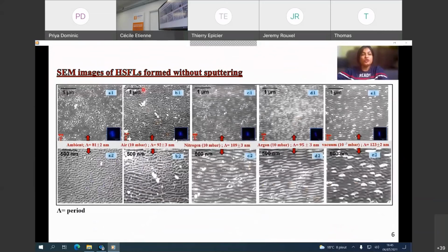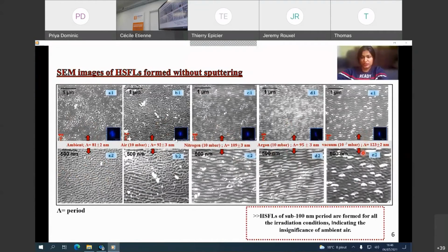So going through the results, first we see the images of HSFL formed without sputtering. We have beautiful HSFL structures, as you can see from the figure, of very small period, which are parallel to the polarization direction of the laser, for ambient condition: air 10 millibar, nitrogen 10 millibar, argon 10 millibar, and vacuum 10^-7 millibar. And the formation of these structures under different gaseous conditions, even in the absence of any air, that is under vacuum, indicates the insignificance of ambient air for the formation of this kind of structures.